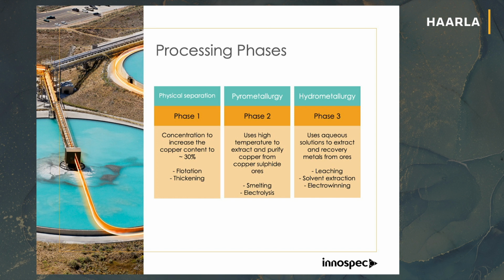Now, the assumption there is that, well, that's really good because you get 99.99%. But the problem is you get 99.99% on the electrode, but you've actually got probably somewhere between 5 and 10% of copper that's gone into the tailings. How do we actually get that out? That's a big number. So how do we actually improve that process?